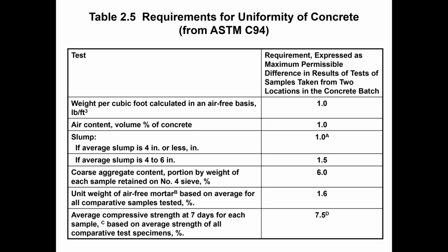Our coarse aggregate content should be within 6% over our three samples. The unit weight of the mortar should be within 1.6%, and the average compressive strength at 7 days should be within 7.5%. All right, so again, this is three samples that are taken from the same truck, and basically this is an indicator of how uniformly that truck is capable of producing a batch of concrete.